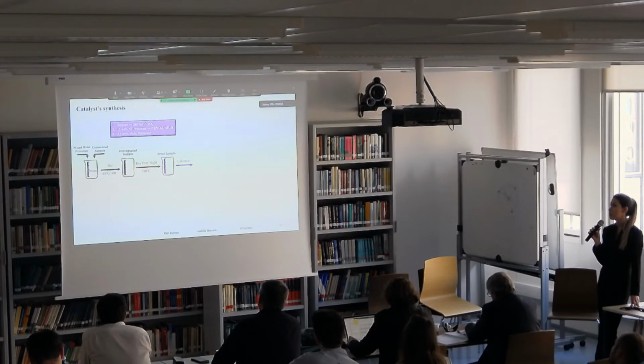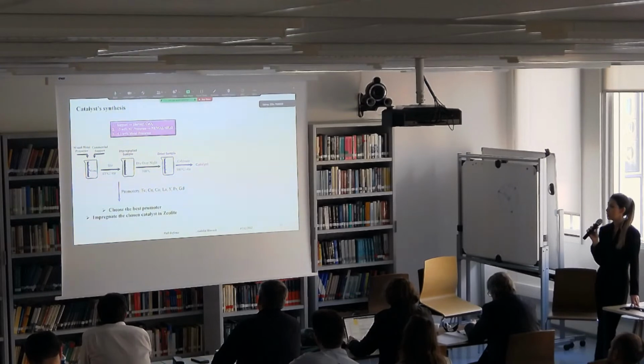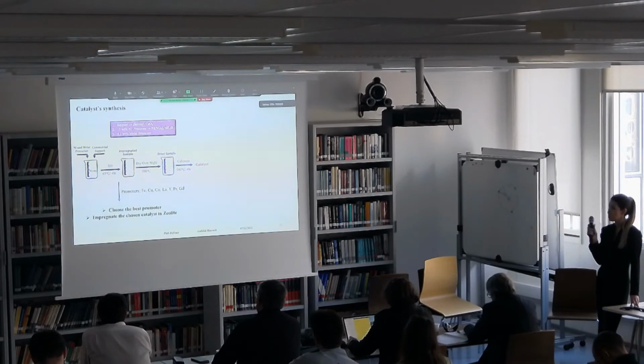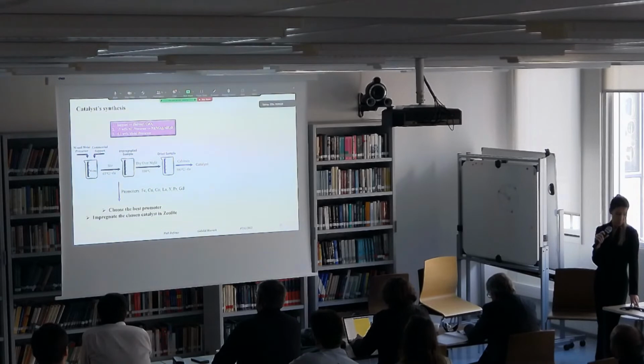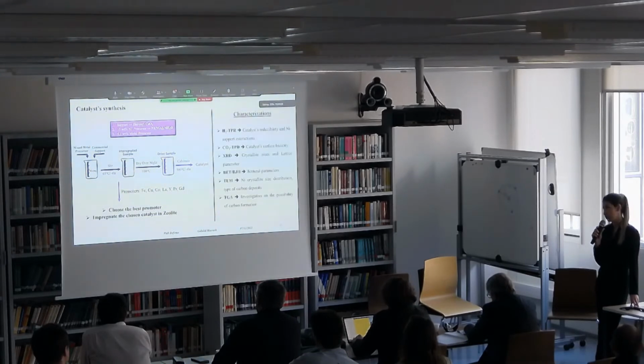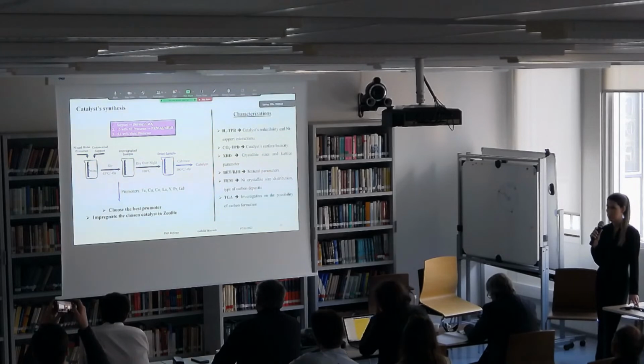So the catalyst was synthesized by the wet impregnation method. All the materials were mixed together and stirred at 65 degrees for 4 hours. The impregnated sample was then dried in an oven overnight at 100 degrees. The resulting sample was calcined with air at 500 degrees for 4 hours, and then the catalyst was promoted with the mentioned promoters in order to choose the best one, and then later impregnated in a zeolite. Obviously, several characterizations were done in order to understand the physicochemical properties of the catalyst and to be able to predict their behavior in catalytic performance.